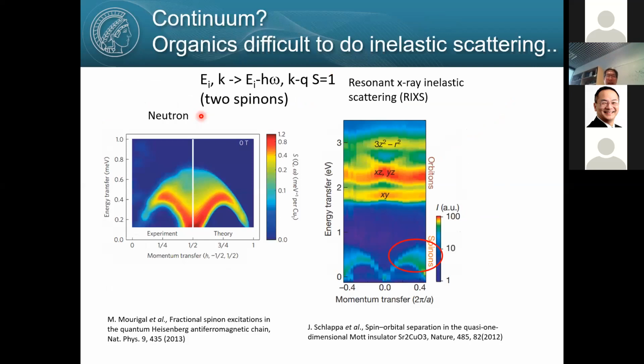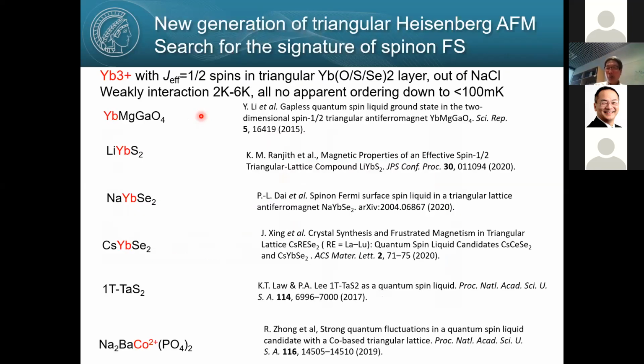Okay, and of course you may ask me, in order to confirm spinon fractionalization, we should see continuum excitations using neutron inelastic scattering. But unfortunately, those organics are full of hydrogen, and they strongly absorb neutrons. The scattering cross section for light elements is small, and it's hard to make that kind of experiment. Okay, but recently, fortunately,